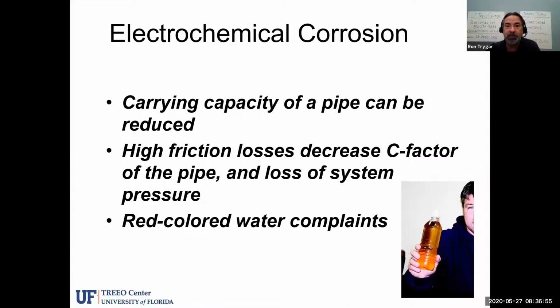All right, so electrochemical corrosion. Again, the carrying capacity of the pipe is reduced. We can't get the same volume of water through it. People start to complain about low volumes of water. They don't get the same pressure that they normally have, so the pressure starts to fall, and we decrease the C factor. Remember, that's the internal roughness, or rather smoothness of the pipe. And we start to get red water complaints, things like that. All of these bullet points on this list are very important for you to recognize, because they are all indicators that corrosion is happening somewhere in your water system.